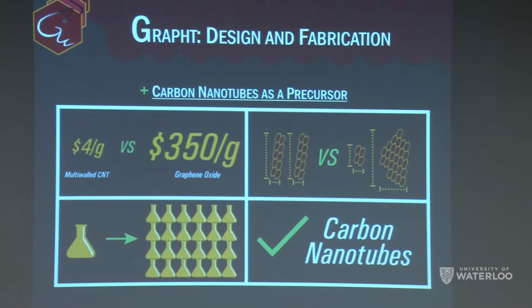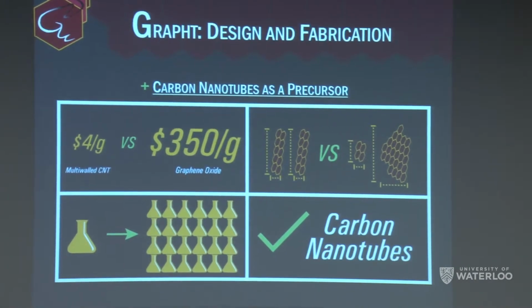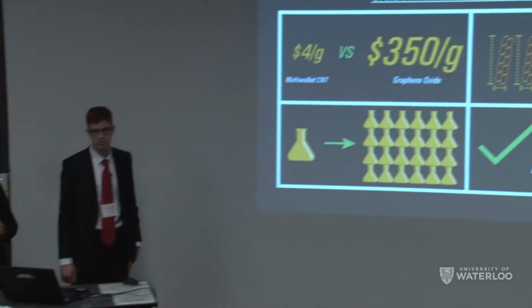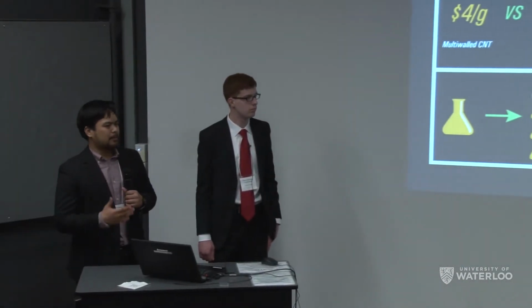On top of that, when you produce graphene oxide through the Hummers method using graphite and a sonicator, you're just hoping that flakes come out and go into the solution, and you have no control whatsoever over the platelet size or the size distribution. But if you start with carbon nanotubes, you already know the diameter and the length of carbon nanotubes. So when you unzip these carbon nanotubes, you know the exact size of your graphene ribbons, which gives you another parameter to play with when you're optimizing mechanical properties.